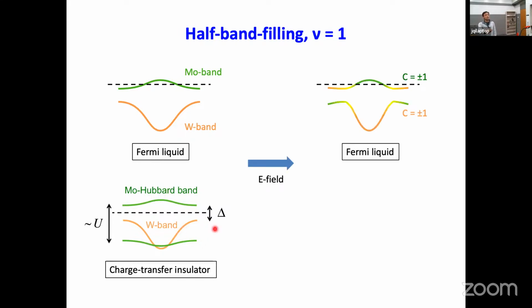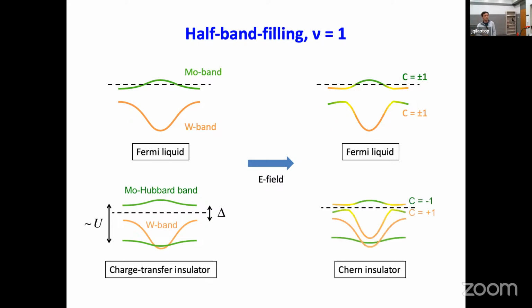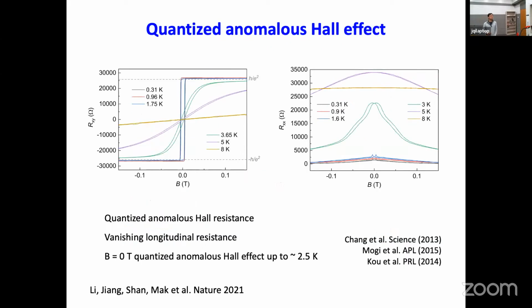Well, after band inversion, of course, without any correlation, it's still a half-filled topological band. It's still a Fermi liquid. But of course, with correlation turned on, you may expect that the energy gap still opens up at the Fermi energy, and you may have some chance to get an interaction-driven Chern insulator. I think people also call this a topological Mott insulator because it's a Chern insulator driven by interaction.